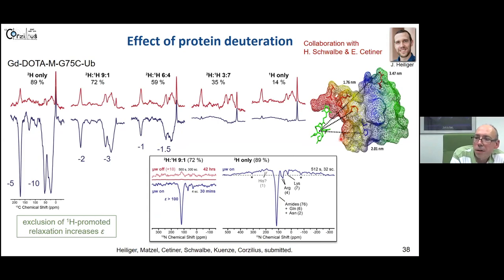But recently we have seen that if we directly hyperpolarize N15, we can achieve enhancement factors on the order of at least 100 or even a few hundred, we think, in this case. But we have measured, I think, over a full week the off signal and still haven't seen anything. So it was not really possible to quantify the enhancement factor in this case. But we have been able to show that we can actually follow the DNP polarization as it is transferred from the electron spin to N15s directly. This is not the actual numbers that we were able to measure. This was just a teaser for an idea that we had.